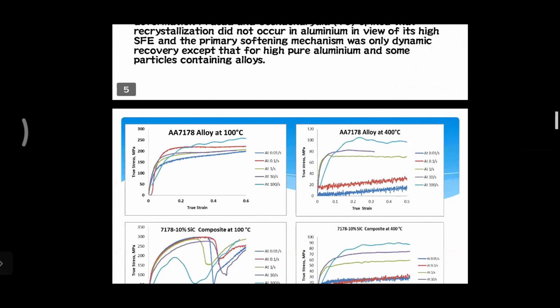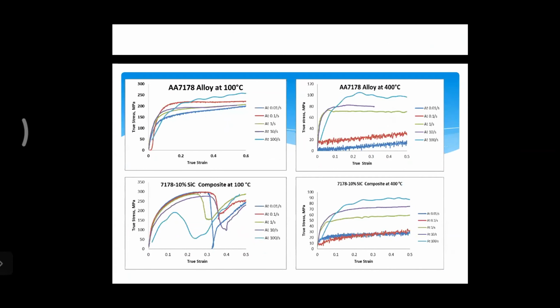Here in the graph, I am presenting the 4 different flow curves for 7178 alloy at 100 degrees centigrade and 400 degrees centigrade. We see how the flow curves behave on increasing the strain rate: on increasing strain rate, the compressive stress increases. And on increasing temperature, it decreases because the material softens, so the stress curves decrease.